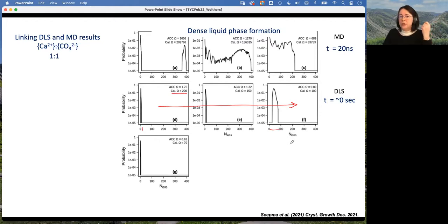which makes sense if you look at crystallization mechanisms. If you have a very high driving force like here, you'll have lots of nuclei forming rapidly, so you end up with many small particles. But if you're in a less supersaturated condition, you will have less nucleation and more growth dominated system, and that's what we think we see here.